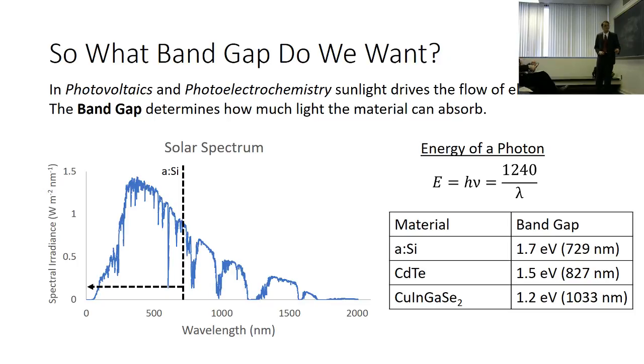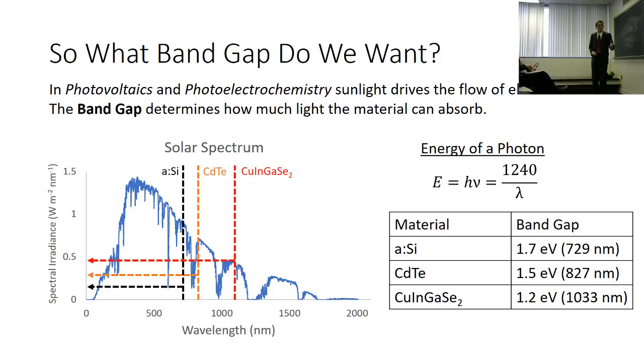For example, silicon, a common solar cell material, has a band gap of about 1.7 electron volts, so it absorbs everything higher in energy. Another material, cadmium telluride, has 1.5 electron volts, so it absorbs even more. This new material, copper indium gallium selenide, being explored for solar cells, can absorb even more. Now you might be noticing a trend: why don't we have the smallest band gap possible, or no band gap at all?